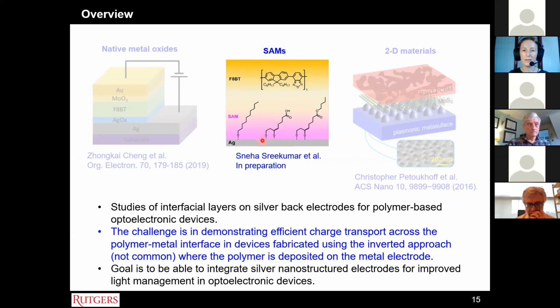So the idea was to use these lipoic acid-based SAMs where we could potentially get better coverage of the silver and may even improve the stability of the silver, compared to more traditional SAMs used for organic optoelectronics like 1-decanethiol.